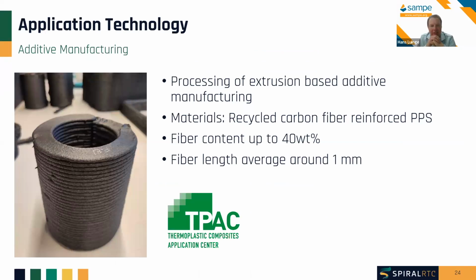Looking at additive manufacturing, so tests performed at the Thermoplastic Composite Application Center, let's say a brother of the research center, to really look at applying and focusing on small and medium enterprises, where we looked at, okay, can we print this material with high fiber content, as high as possible, and a relatively long fiber length. So this study is ongoing. Well, it's processable, and we'll look at further processing and testing on the way. But I think the first conclusion is, okay, it looks good in terms of processing.